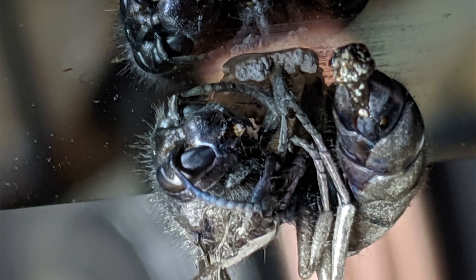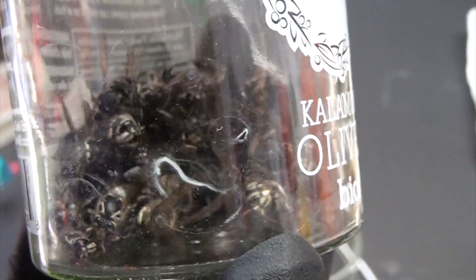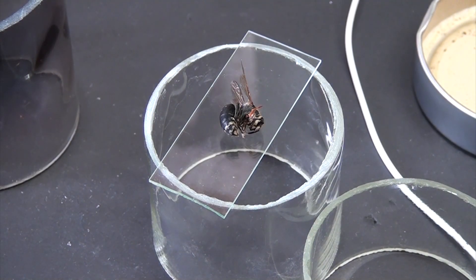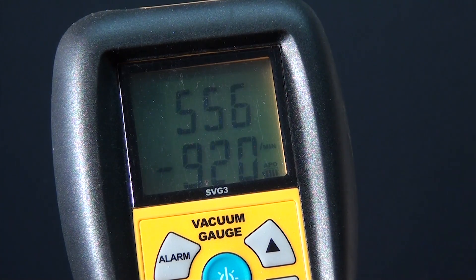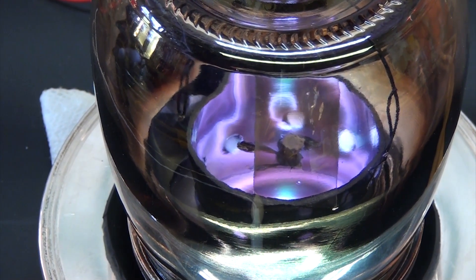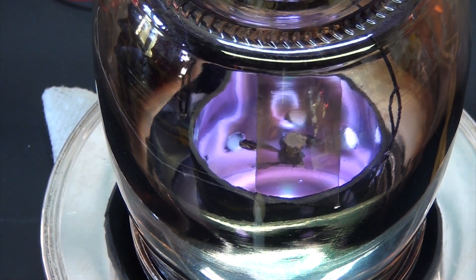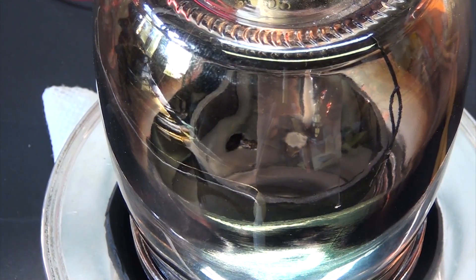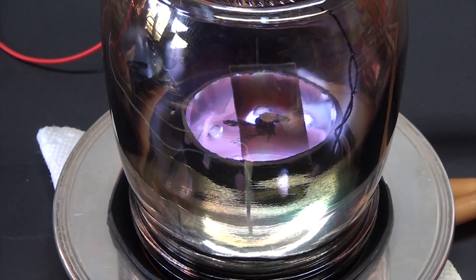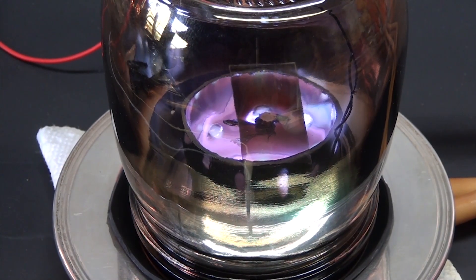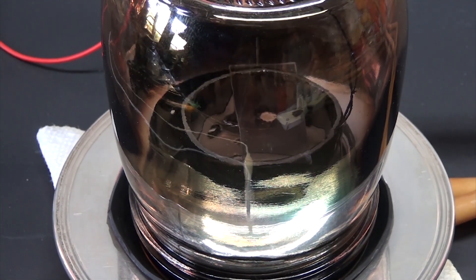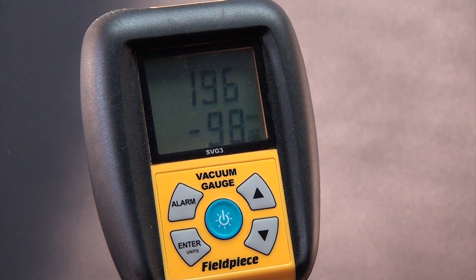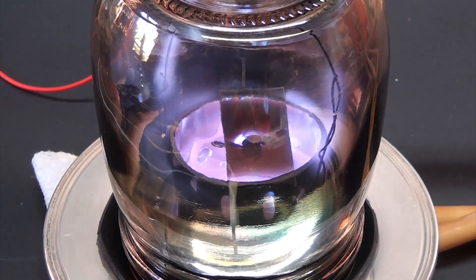Next, I promised you Metal Hornet, so here we go. My friend brought me these from a nest he had to take down a few days ago, and so they were still very fresh. This is actually an issue, as fresh translates to full of water, which is the most annoying contaminant you can get in a vacuum system like this. So at first the system wouldn't get past 500 millitorr. I thought for sure this meant that no metal would fly, but when we hit the power, sure enough I got the distinct blue glow of silver plasma, before it quickly got extinguished as the chamber pressure continued to rise. After a few of these cycles, the hornet was actually starting to get covered, and the pressure was dropping. In essence, we were plasma drying the hornet gently, while also covering it in metal while it was fresh. Eventually we managed to get the pressure down to the usual operating levels as it dried out, and got a beautiful silver coating on the hornet. Now it looks like something straight out of Black Mirror.